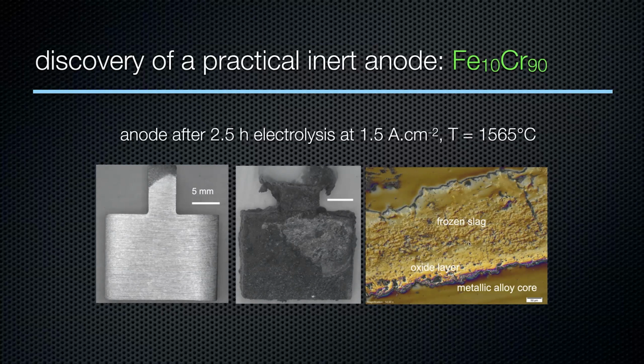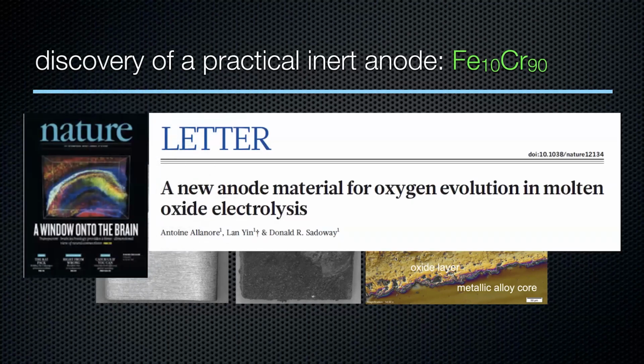And when we did some cross section of it, we see that this is the metal alloy core, and the slag is frozen on the outside. And you can see this oxide layer in between, and that oxide layer is thick enough to protect against attack, because remember, oxygen bubbles are forming here at almost 1600 degrees Celsius, and yet they don't fully oxidize the core of the electrode, because that electrode is protected by this surface film, which is still thin enough to allow electrons to go across and then react with the oxide ions to form oxygen gas. And so this we published in Nature, and as a result, it gave us some credibility.